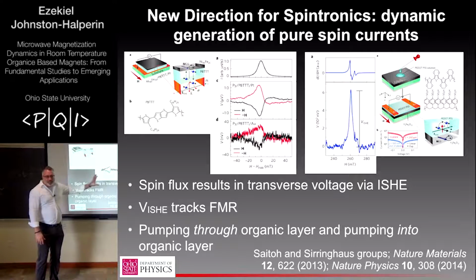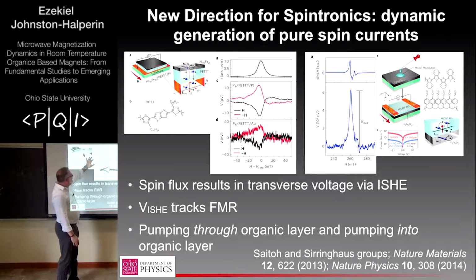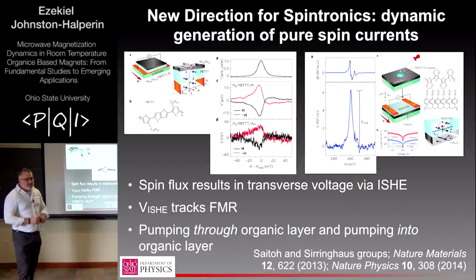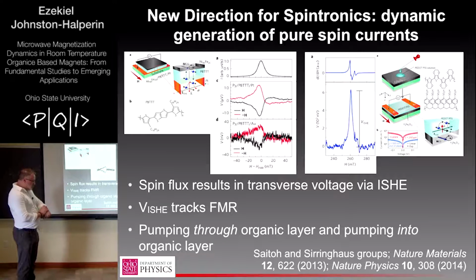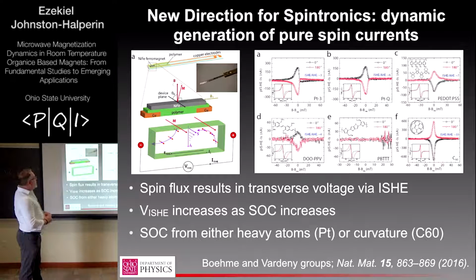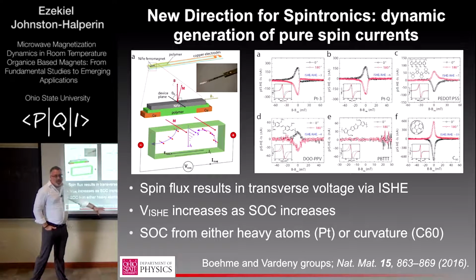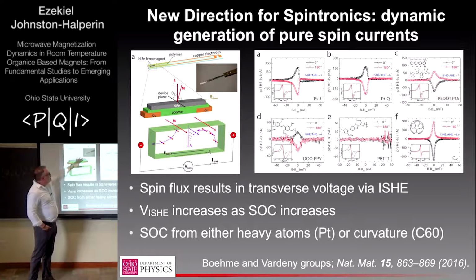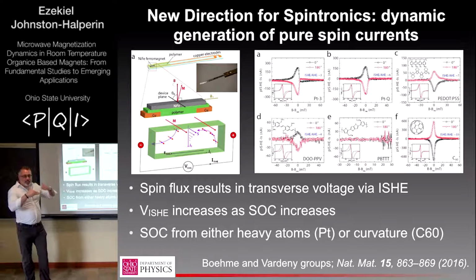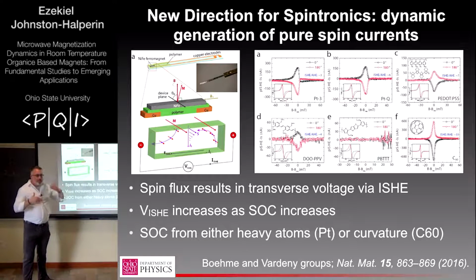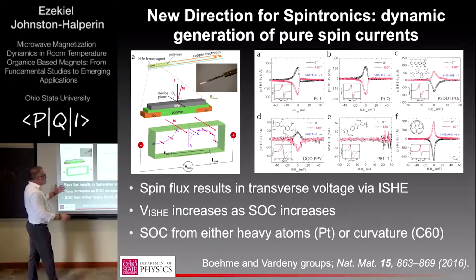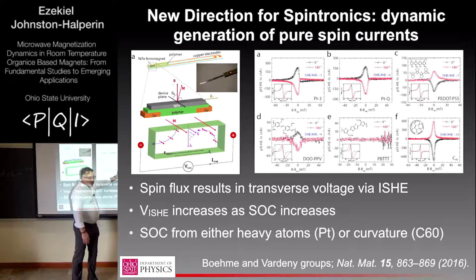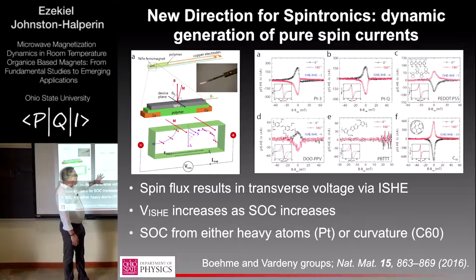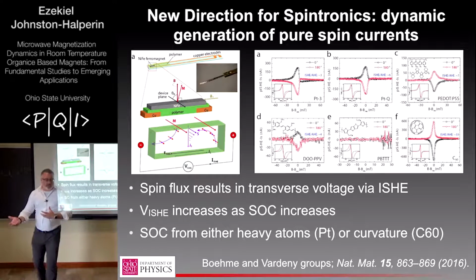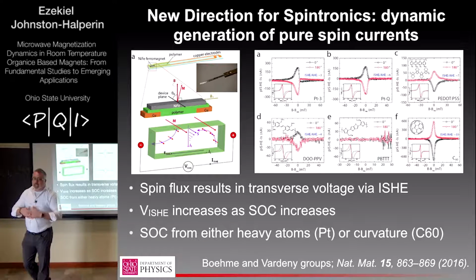So these experiments, though, if anybody has looked into this field, are messy and hard to interpret. The shortest way to say it is, that's a 1 microvolt signal in an FMR cavity where you're putting in hundreds of milliwatts of microwave radiation. So artifacts are a big problem, which is one of the reasons that more recently I was very excited to see this collaboration out of the Boehme and Vardeny groups in Utah, where they did some very clever things in designing their microwave environment to effectively put an in-parallel capacitor with their sample, which shorts out many of the artifacts, and they did some careful systematics. They also systematically varied the molecule to vary its spin orbit coupling, and used the molecule itself as the spin Hall material. And so demonstrated, I think, very interesting spin pumping into an organic system.